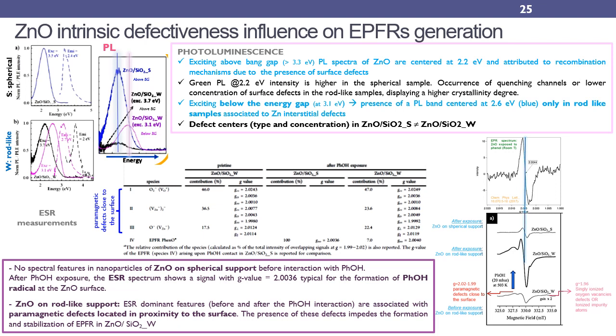On the contrary, ESR spectrum of zinc oxide on spherical silica is collected only after the exposition of vapor, revealing the presence of a weak signal attributed to the phenol radicals. These results prove that the presence of different surface defects in zinc oxide can either hinder or create the environmentally persistent free radicals on metal oxide surfaces.